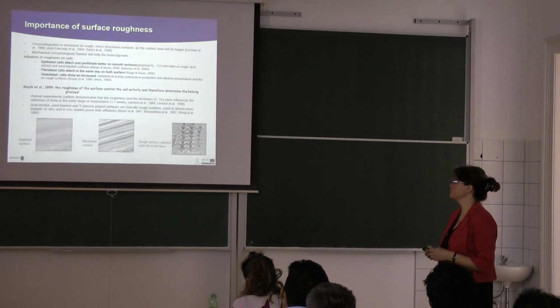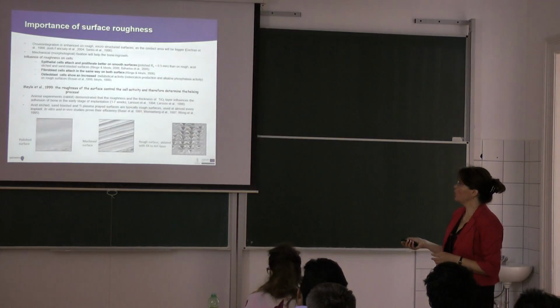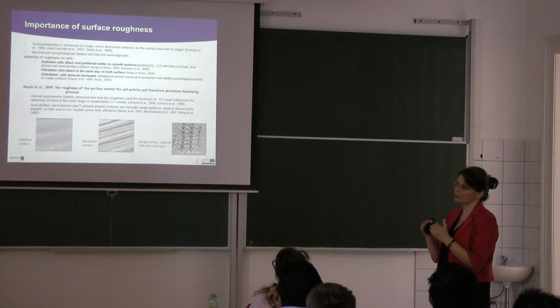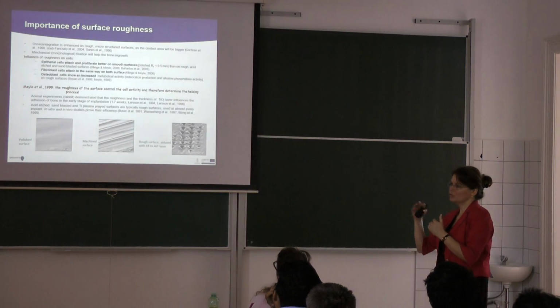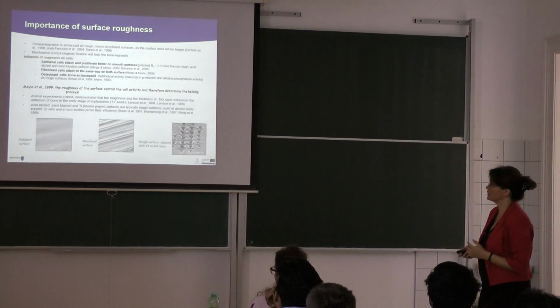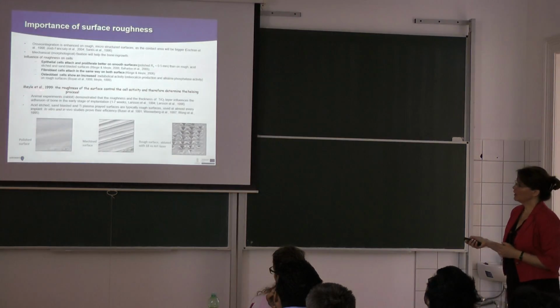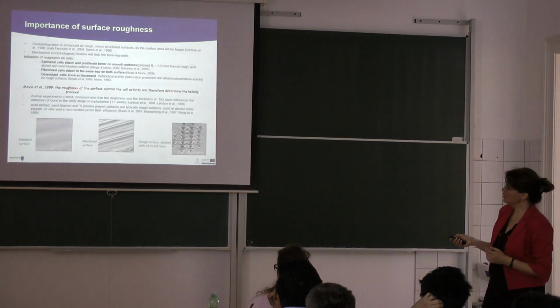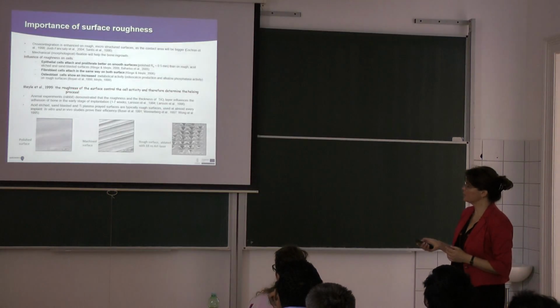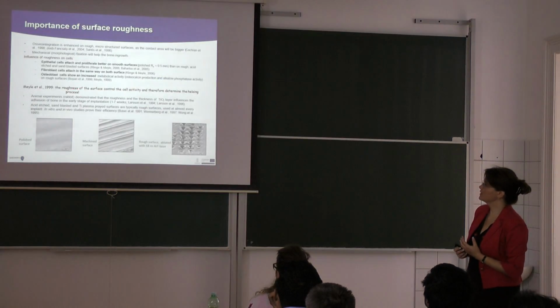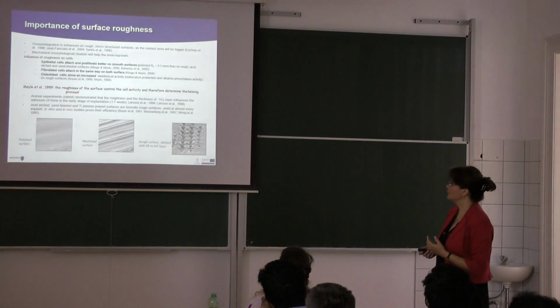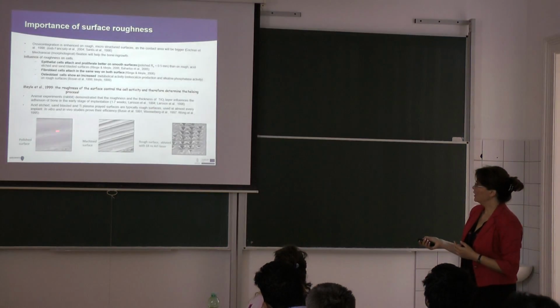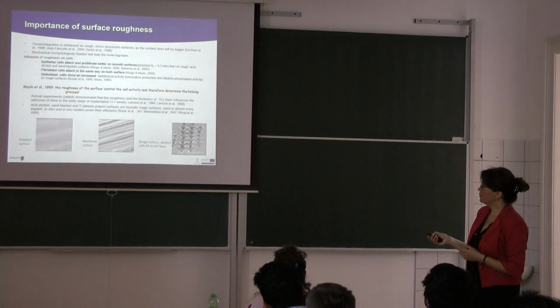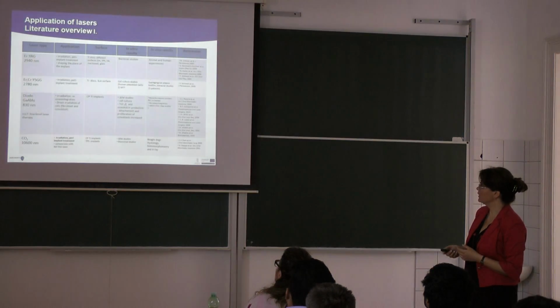the osteoblast cells show an increase in, let's say, metabolic activity on rough surfaces, as I told you, from around 500 nanometers to 2000 nanometers and so on. Meile and his co-workers could even show that the roughness of the surface will control the cell activity and therefore determine the healing process. And you can see these many publications. I was just showing you some laser ablation. I will tell you later on.